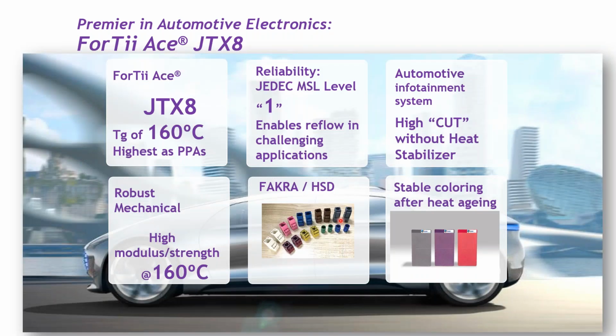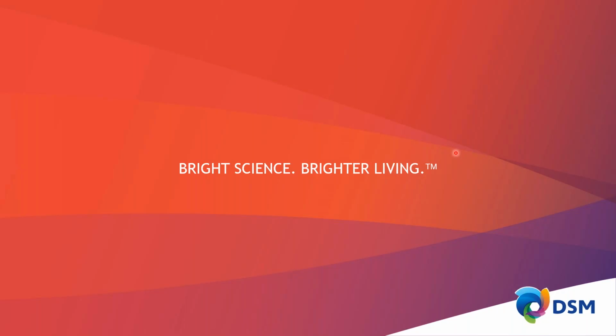And for best in class moisture sensitivity level resistance, so unlimited shelf life and low blistering as it goes through the reflow process, we have the JEDEC MSL level 1 rated JTX8 material. It has a good combination of mechanical robustness, modulus, and strength, and great colorability and ability to retain that color through the reflow process, and operates with a good high continuous use temperature, we call it, without heat stabilizers. So that's the material family for the